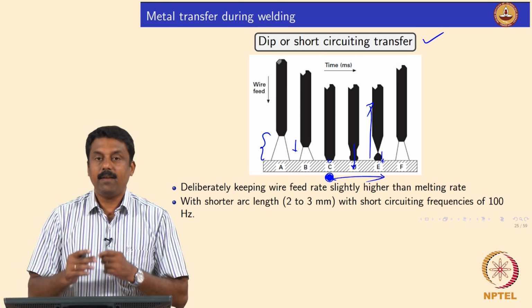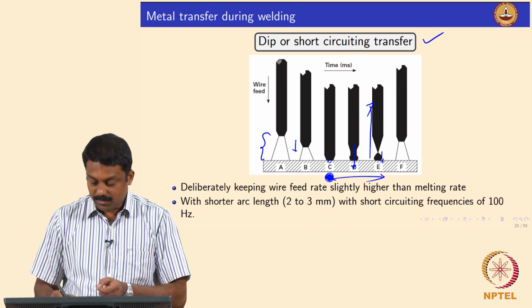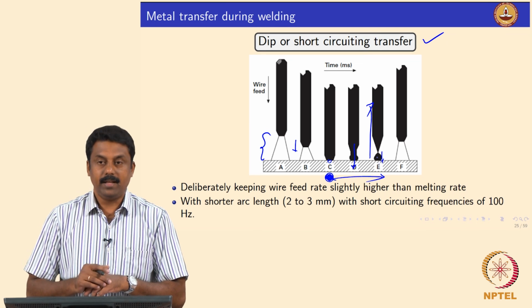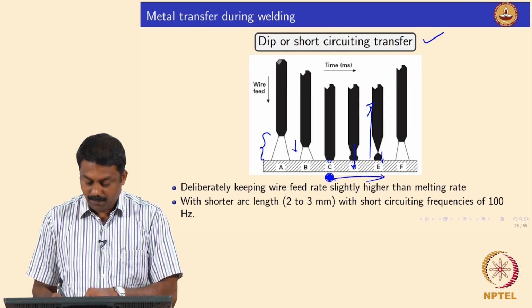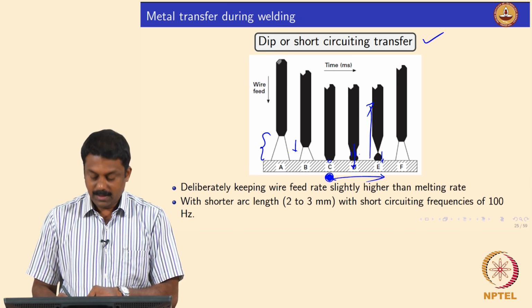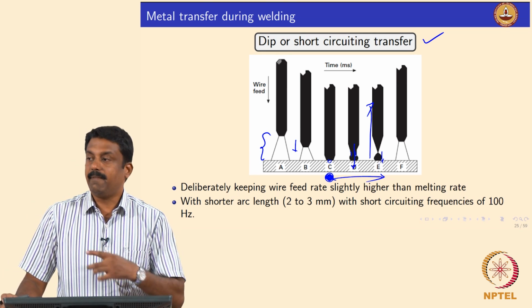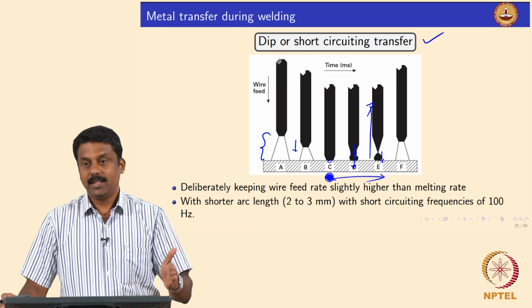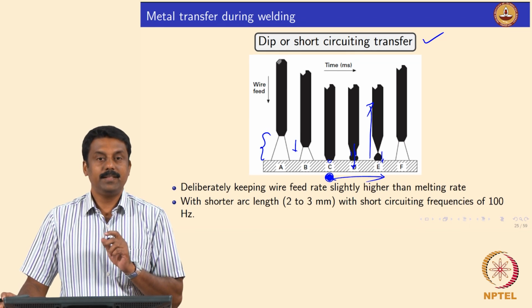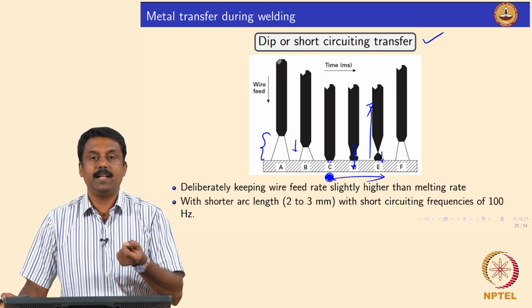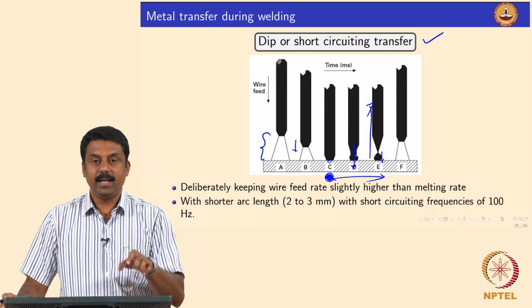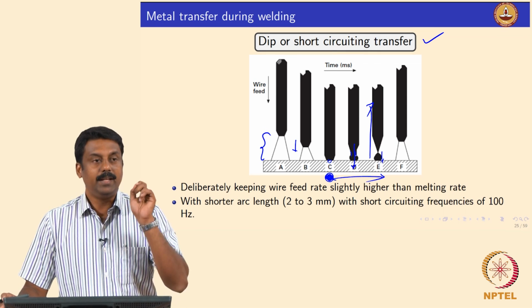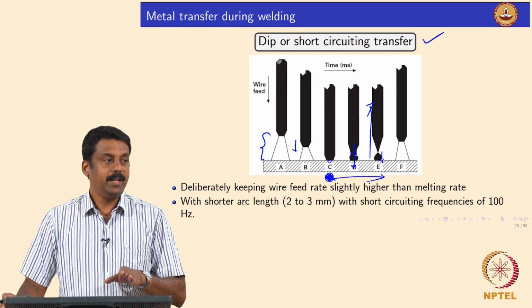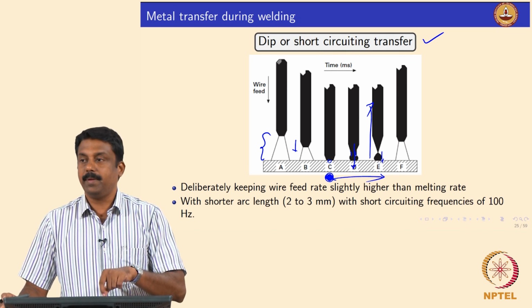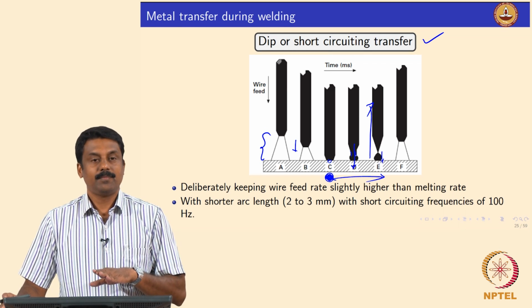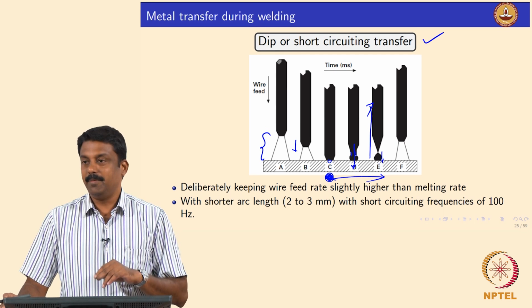And during this process, by carefully manipulating the current voltage waveform, we can transfer the droplet without any explosion. So, that is very critical, because if you keep on passing the same amount of current, when you form a neck, then you increase the Lorentz force so high and you will have explosion. Okay. So, your power source should be capable of turning the current off the moment short circuiting happens, right. Okay. So, by deliberately keeping the wire feed slightly higher than the melting rate, we can establish short circuiting. The moment short circuiting is established, we will have to identify that moment and then switch off the current or reduce the current, okay. And then the molten droplet at the tip can be transferred to the workpiece by surface tension of the liquid pool, right. It is clear. I will show you a video, it will be very clear.